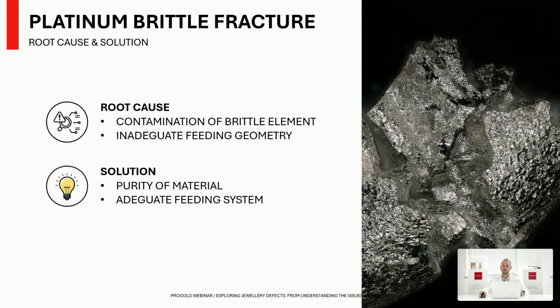How to solve this kind of problem? First of all, the purity of the metal is crucial in order to guarantee the resistance of the material. Contaminating elements like aluminum, silicon, and carbon are dangerous and could derive from contact with the crucible and the investment used for the production. But also, particularly in the new model design, an adequate feeding system needs to be studied in order to prevent localized stress that could lead to cracking.